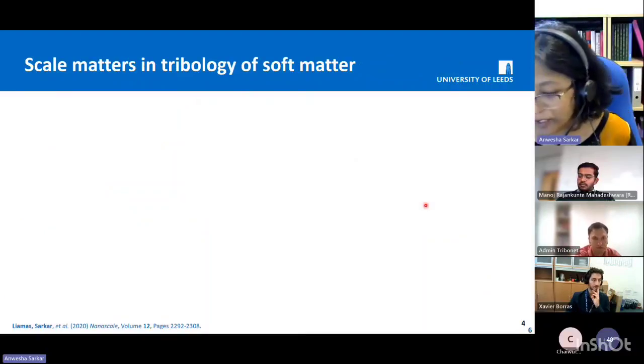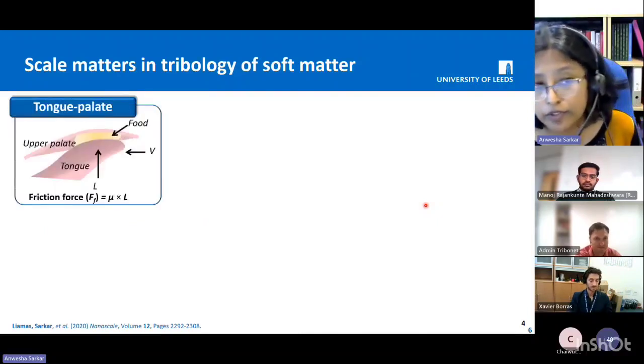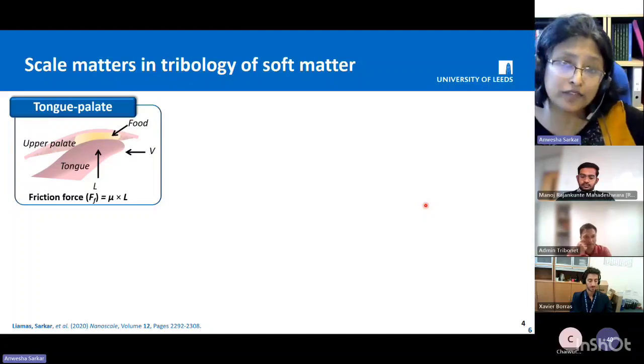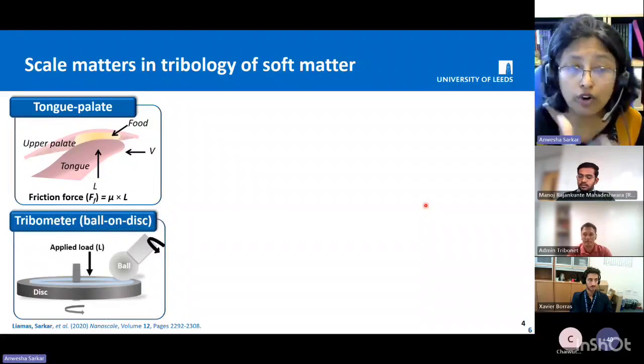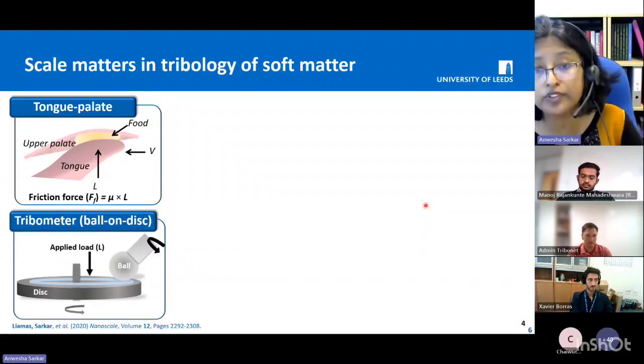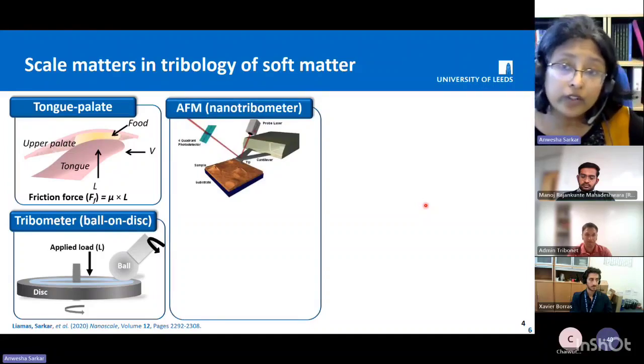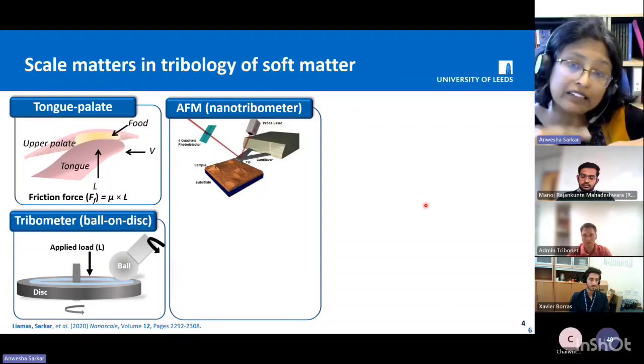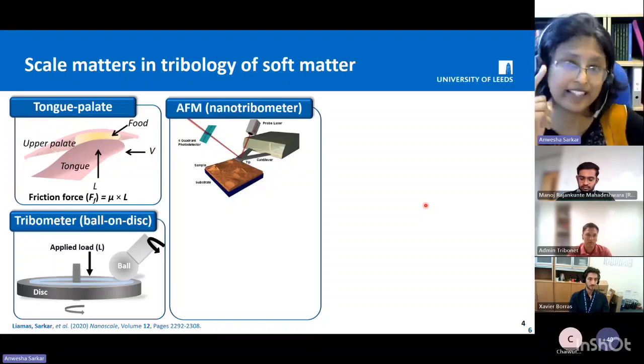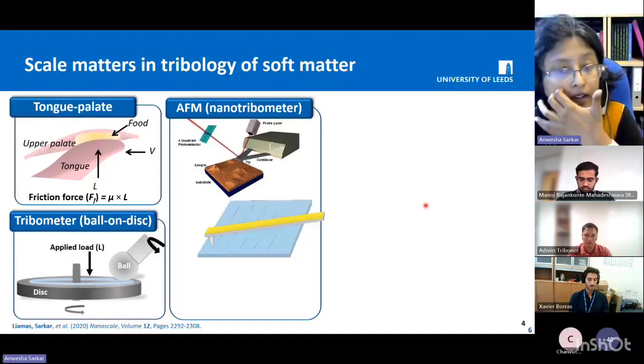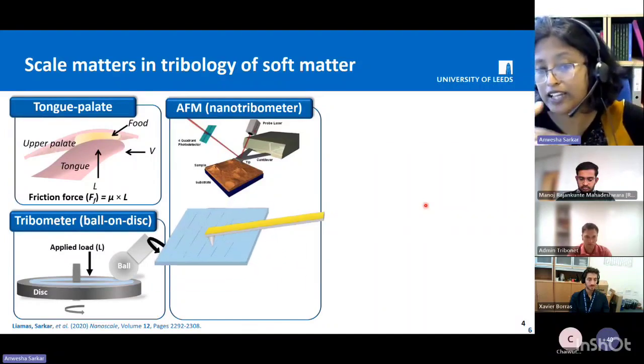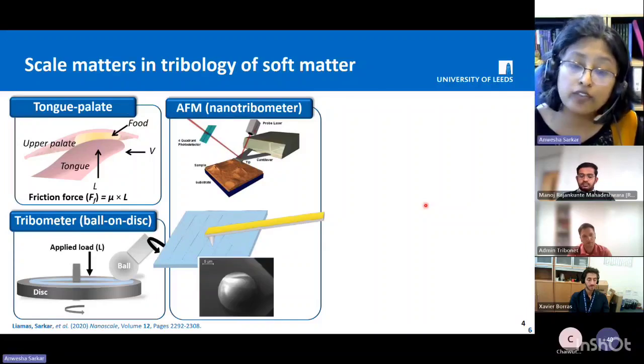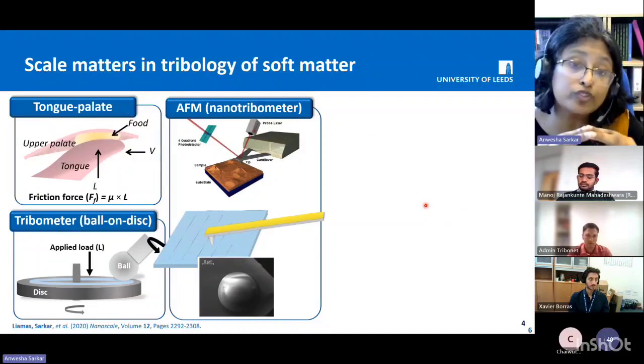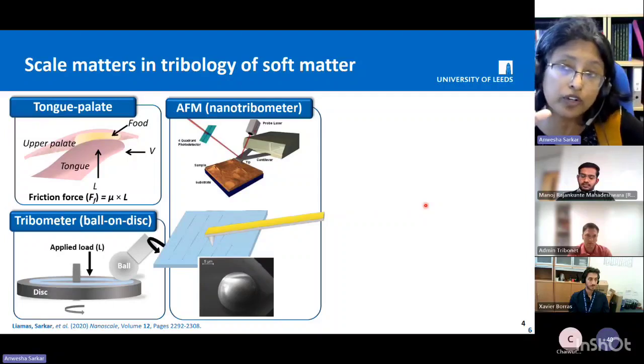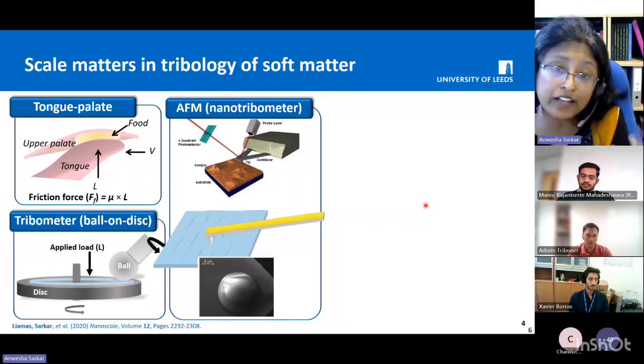Of course, you are a group of tribologists, so you know scale matters in tribology. We are talking about tongue scale, but the tongue is not one surface, it has so many papillae. So we look at a ball-on-disc tribometer, considering it a smooth surface, but we also look at AFM. Why do we look at that? Because then we can identify things at the single papillae level. So not only the full tongue, but the single papillae, and we can understand those interactions. How AFM works is like braille: it reads by touching, and you can get force-distance curves. And in Leeds, what we do with physics is we develop soft colloidal probes. So we don't work on classic AFM tips, we work on soft colloidal probes and try to define the deformability, which is in line with the deformability of a real human tongue.